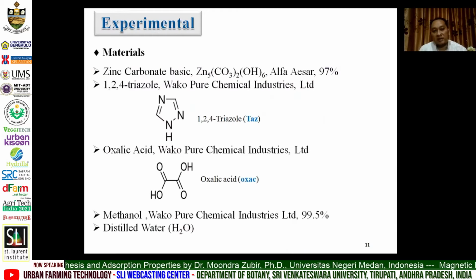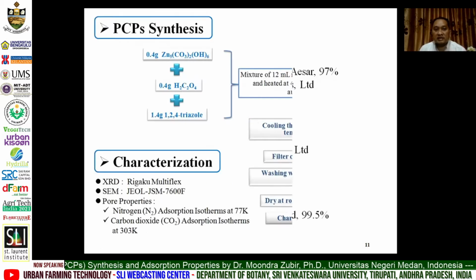This is the experimental stage of this research. For the materials, the metal ion zinc comes from basic zinc carbonate, and we choose two ligands for this synthesis. First is 1,2,4-triazole as the triazole ligand, and then oxalic acid as the second ligand. We use methanol and distilled water as solvents during the synthesis.